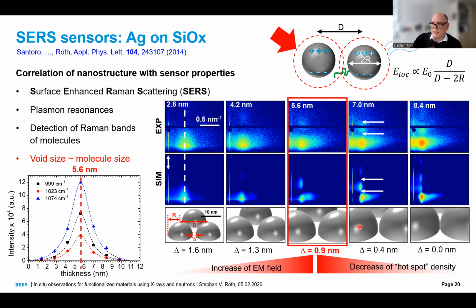When this is 1, the clusters touch each other. So we have several methods to verify the percolation. And just as I mentioned, if you make an experiment and you decide you want only to follow this peak, this is fully sufficient. When you want to know the distance, already from the distance, under some assumptions, you can deduce electrical properties. So the depth of information depends on the depth of analysis and how much time you want to incorporate.